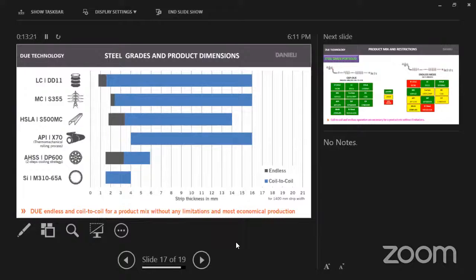This silicon grade is a major one, you can say the high value grade. You have to go in coil-to-coil mode, meaning one slab is equivalent to one coil. In endless mode, it is not possible to produce silicon grade. It is better, because for the silicon grade I need a finishing mill temperature. Before entering the finishing mill, I need a higher temperature. So it will be better to produce silicon grade in semi-endless mode. Because I can take a mother slab of around 80 meters and then feed it into the finishing mill with higher temperature using the induction heater, then I will get better quality silicon grades in Danieli universal endless.